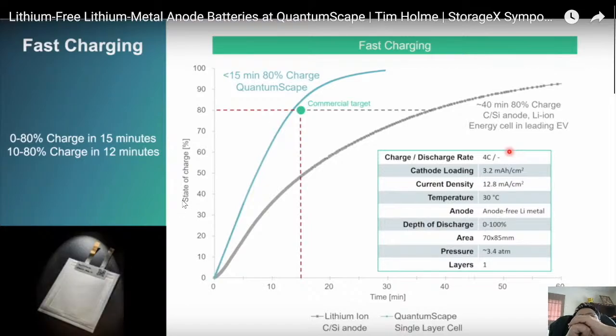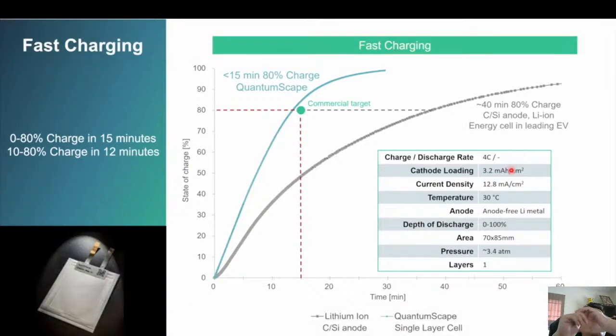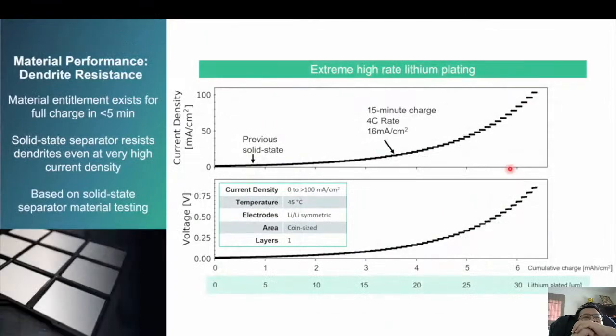It's the same cell that can do fast charge. Then we wanted to really test dendrite resistance of the separator itself. So we took the separator out of a cell and did a stress test where we just increased the current density and saw at what current density the separator could withstand. So we're passing small amounts of lithium and then increasing the current density, pass more lithium and increase the current density, and continue to increase the current density here.